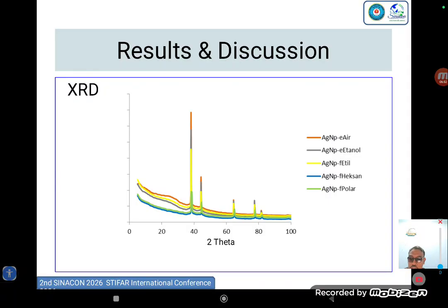Furthermore, to determine the crystal structure of silver nanoparticles, the samples were analyzed using XRD, X-ray diffraction, and the data are presented as follows. XRD analysis confirms FCC crystalline structure across all samples.